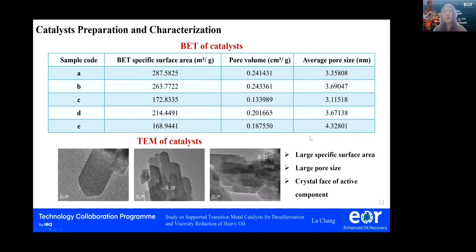The BET data of the carrier and the catalyst are shown in this table. The largest specific surface area can promote the contact between the active components and the reactants. And the large pore size can permit the free entry and exit of heavy oil macromolecules. And these 3 TEM scanning pictures show the crystal face of the active component.